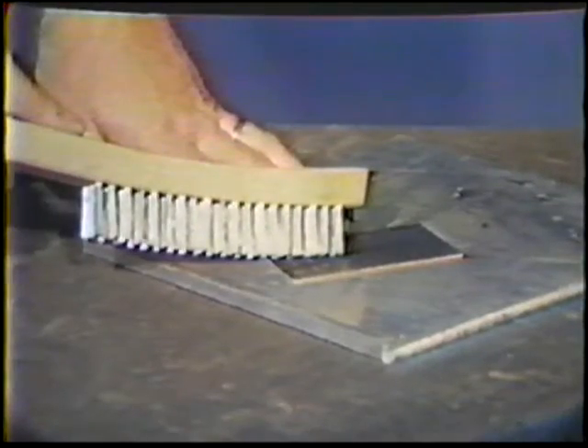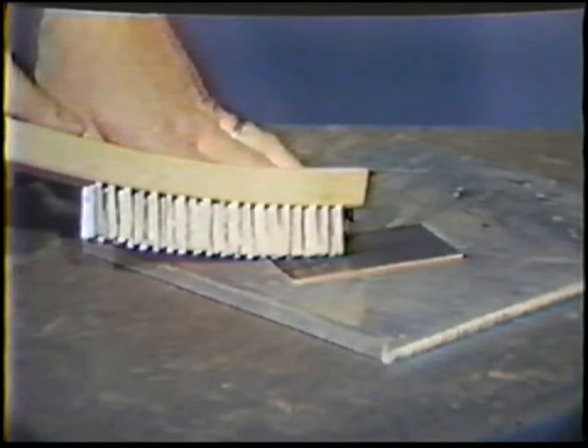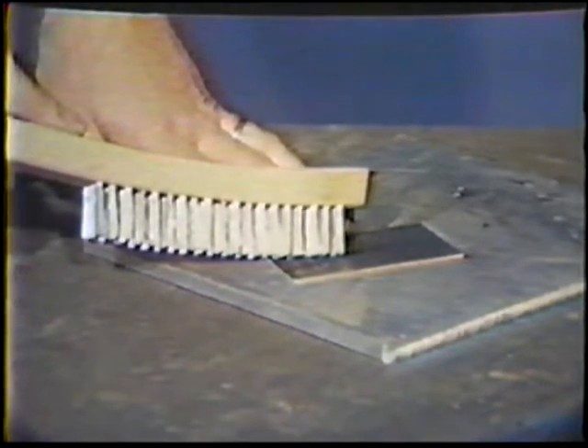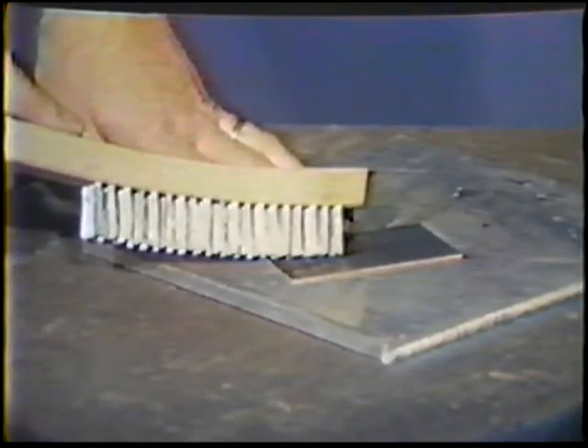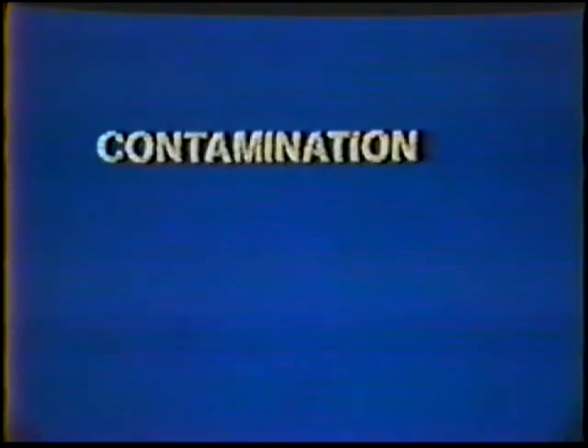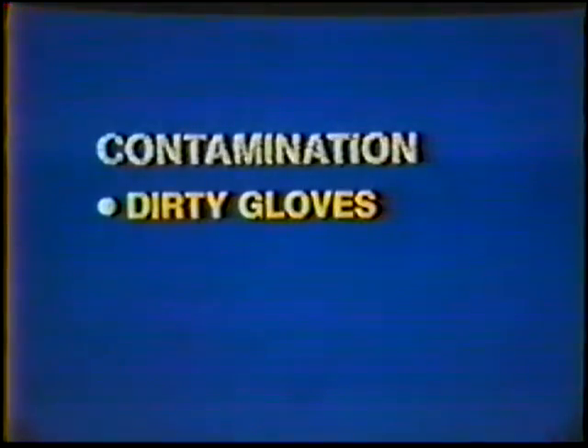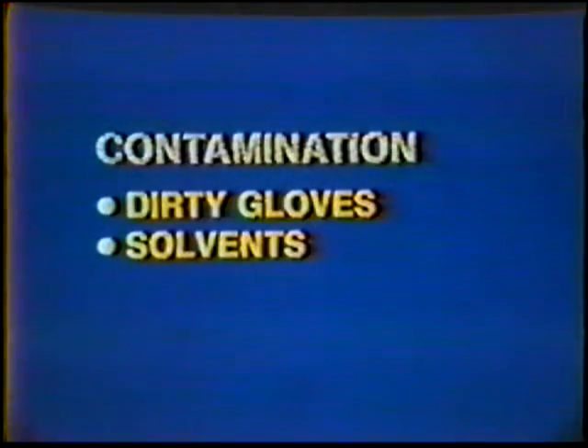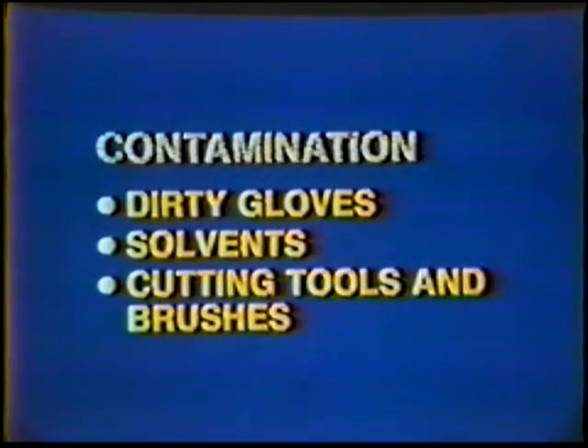Careful cleaning is much more important when working with stainless steels. Contamination can cause poor welds and loss of corrosion resistance. Contamination comes from many sources: dirty gloves, cleaning solvents left on the metal, cutting tools and brushes which have particles of iron, zinc, or other metals on them, and others.